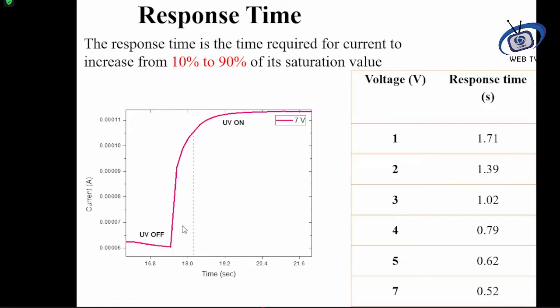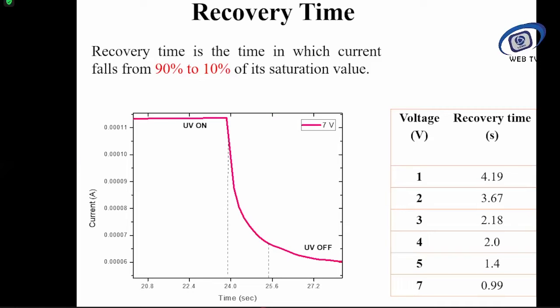And this is the response time. We can see that the response time at 1 volt is 1.71 second, and at 7 volt is 0.52 second. Recovery time means that when we turn off the UV light, the current drops, and this drop of the current varies with the voltage. At 1 volt it is 4.19 second recovery time, and at 7 volt, 0.99 second recovery time.